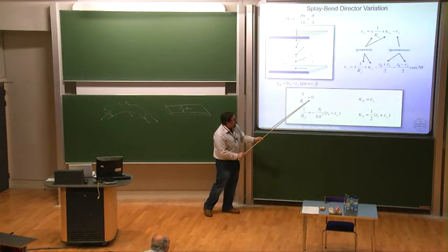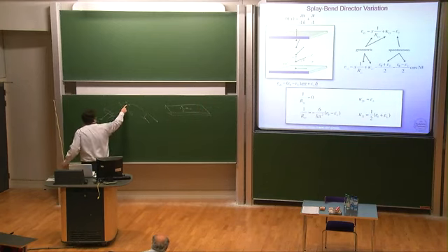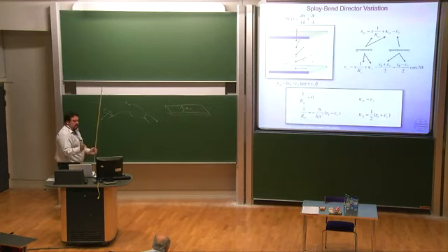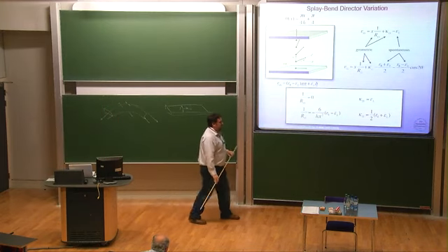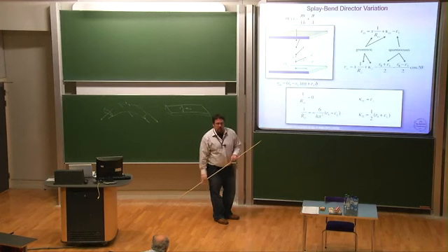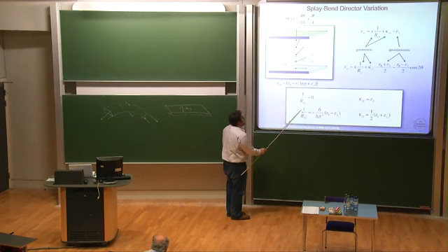But for the bending geometry, in the splay bend case, you don't get any of that extra. You don't get any curvature in the normal direction to the bender. So there's no higher order worries, which you would have if you had that extra curvature that I'll go into detail in a second, because the next system will have it very strongly.